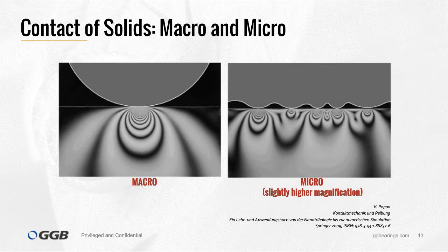From a macro perspective, it looks as always. On this sample, we see a steel ball on a flat steel surface, and it seems to be an ideal contact. The microscopic view, however, shows that the surfaces only touch each other in those areas where we have these protruding surface irregularities. We tribologists call the sum of all these small areas the real contact area of a tribological contact.